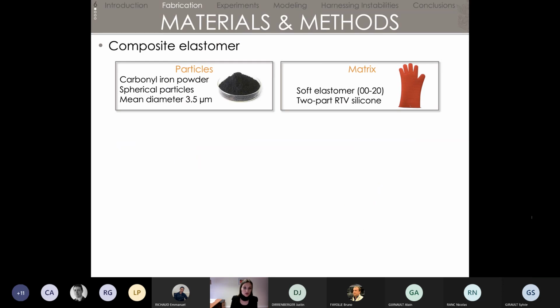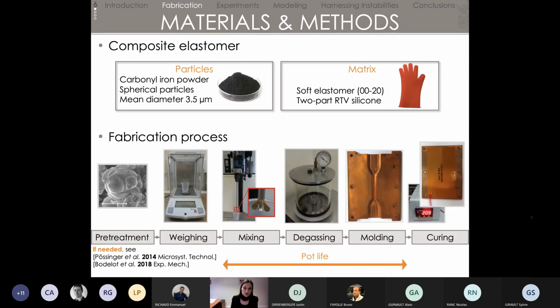So the particles that we're using are carbonyl-iron powder. Those are spherical particles, and their average diameter is around 3.5 microns. The matrix here is a soft elastomer, Shore 00-20, so around 40 kilopascal for Young's modulus. It's a two-part silicone, which is RTV, which means room temperature vulcanization. To fabricate them, we have to take our particles, pre-treat them, I'll talk about it right after, weigh the particles and the amount of matrix, mix all that together, then degas the mix and pour it inside the mold, which we can put under temperature to accelerate the curing, even though it would cure within 24 hours at room temperature.